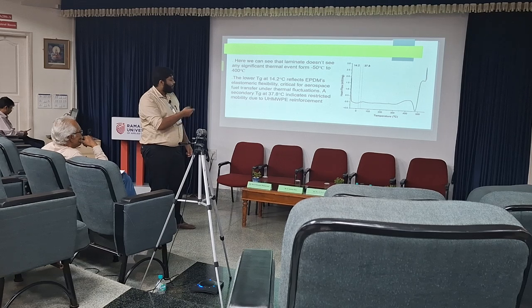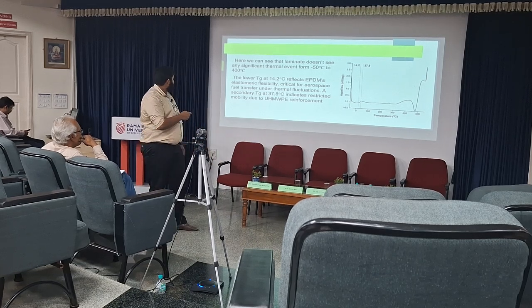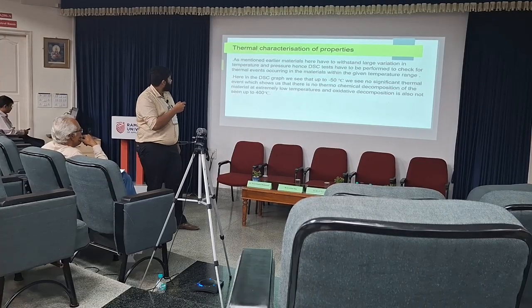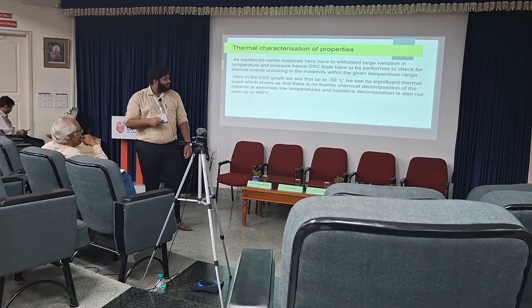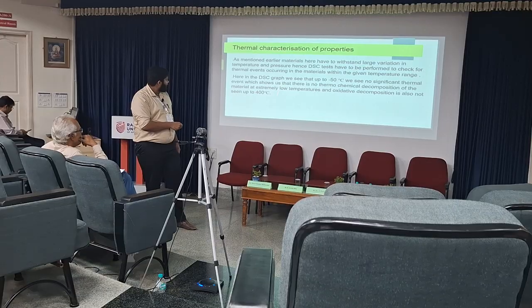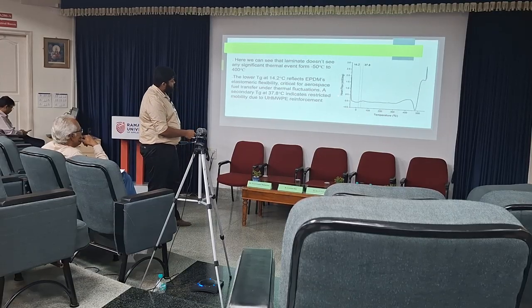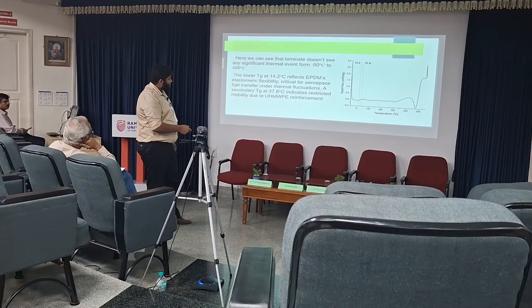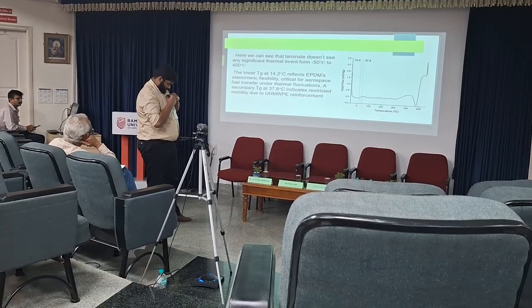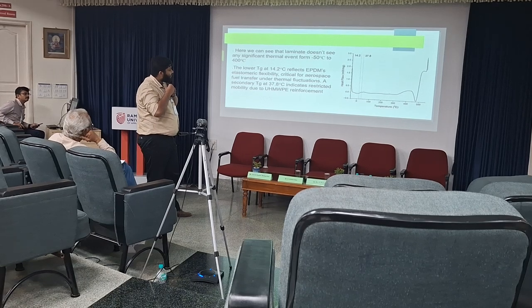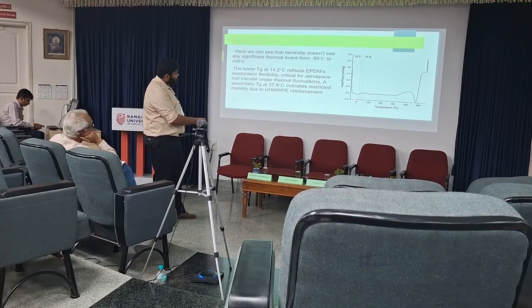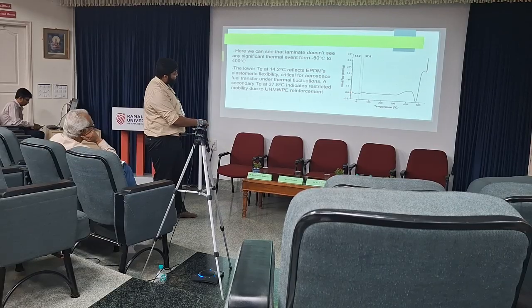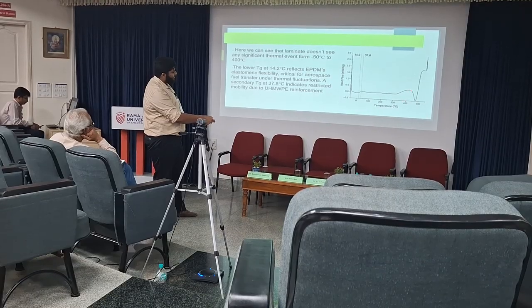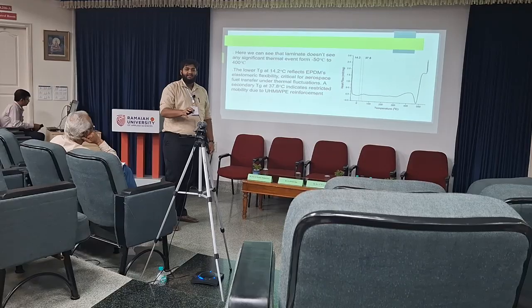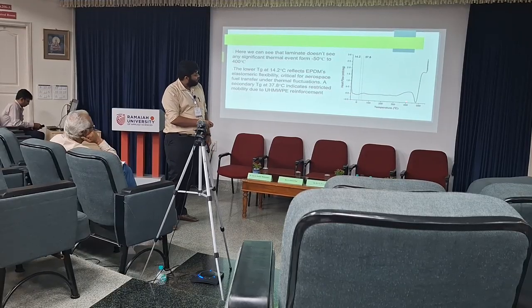So we have conducted both normal DSC and extreme cold level DSC, to check a temperature range of minus 50 up to 400 degrees Celsius. So here if you see, this is the heat flow and this is the temperature. So you can see here the heat flow versus the temperature range graph. So here you can see starting from here minus 50 degrees Celsius up to 400 degrees Celsius, we do not see any significant thermal event. So that means it is stable from minus 50 to 400 degrees Celsius.